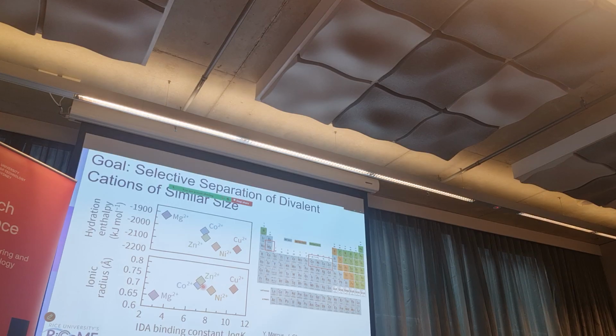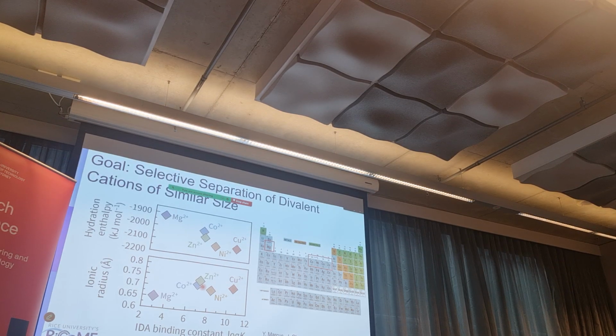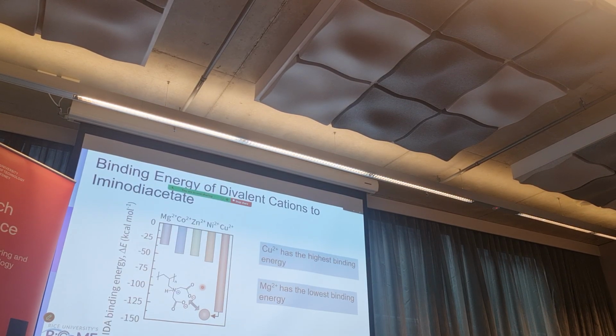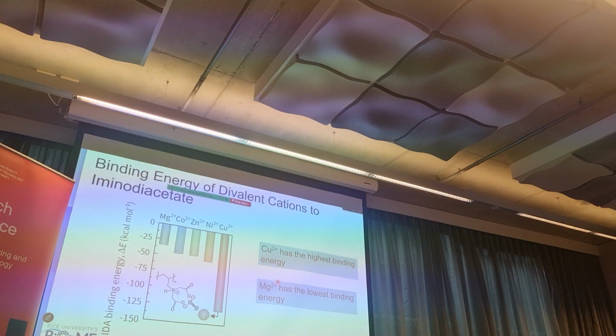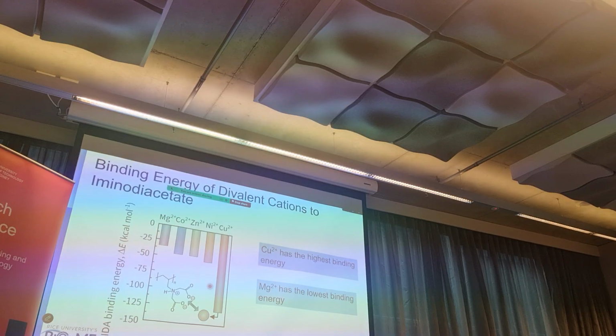So this would be quite difficult to separate, but I said let's try with this iminodiacetate. First we need to study the binding of this iminodiacetate to these metals. So we did some DFT calculations for the binding of iminodiacetate to magnesium, cobalt, zinc, nickel, and copper, and we found that copper has the highest binding energy, and magnesium has the lowest binding energy. These DFT calculations were roughly similar to what you can get from the stability constants of complex formation found in the literature.